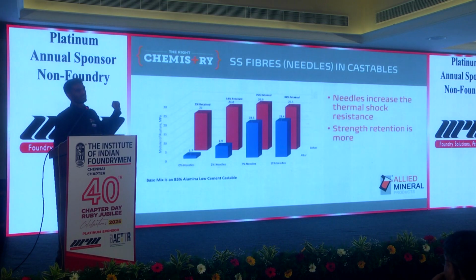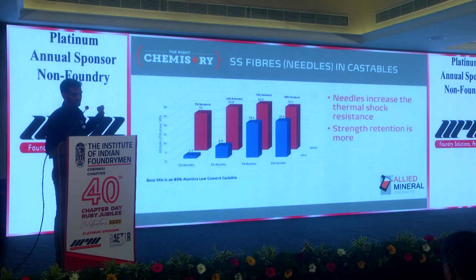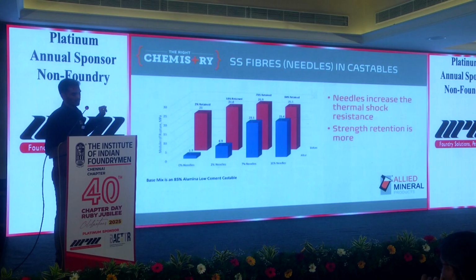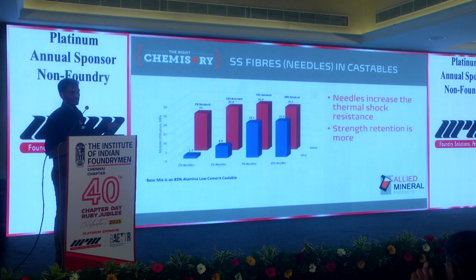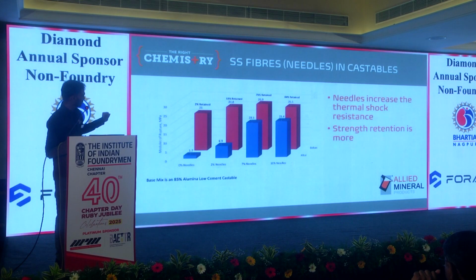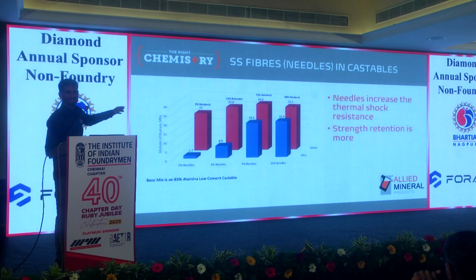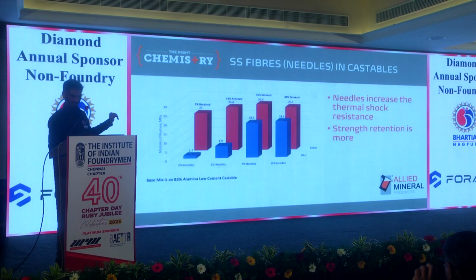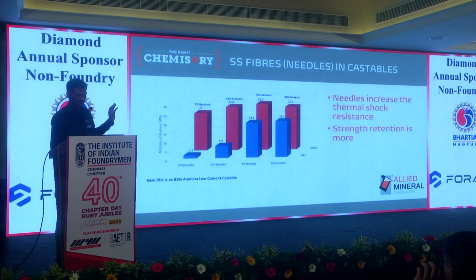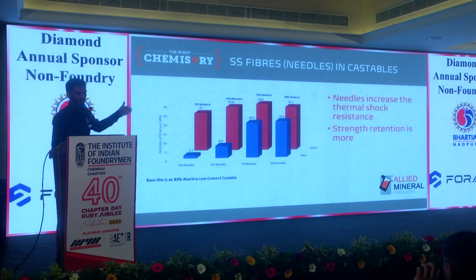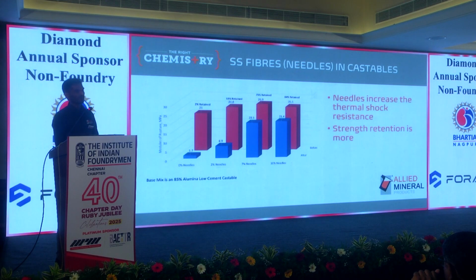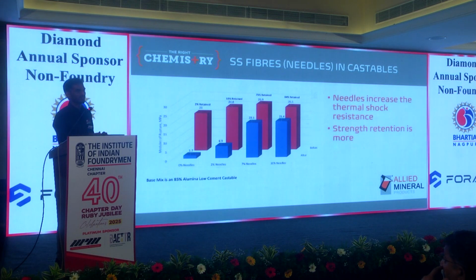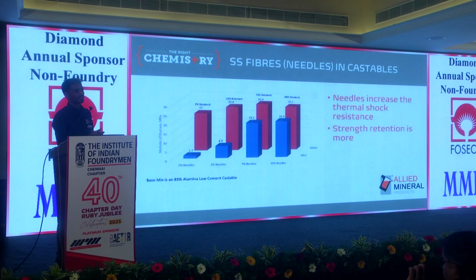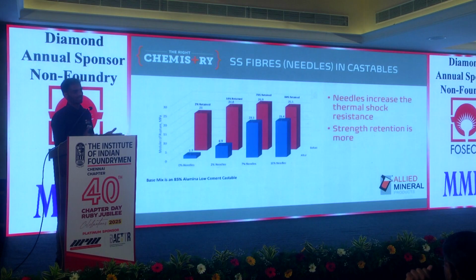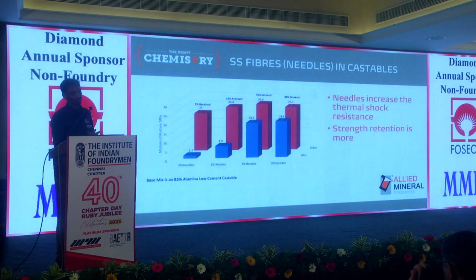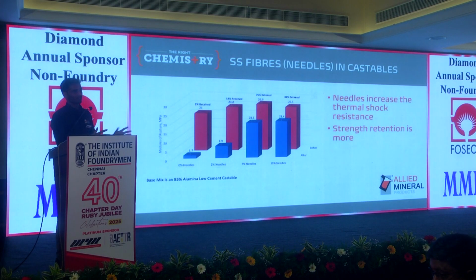So this is what I was talking about earlier with respect to the needle additions. Even if you see the strength retained with 2% needle addition versus 0% needle addition, the strength retained is almost like 21%, am I right, Venkat? 21%, okay. With 2% needles you can see the strength retained, but when you go above 6% or 7%, the strength retained is not that great. It's almost equivalent to the needle addition of 6 to 7%. That's the reason we typically stop the needle addition around 6 to 7%, because there's no value to it. The only thing is you're going to increase the cost of lining. There are very few products which we develop with 20% needles, but those are for special applications where it is required.